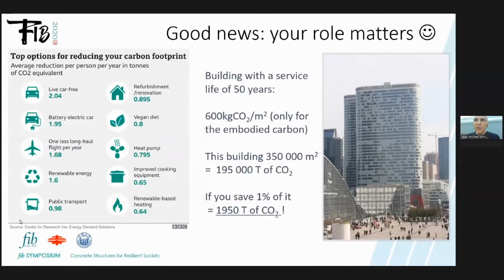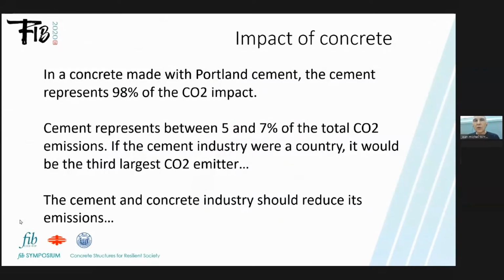If we look at concrete made with Portland cement, the cement represents 98% of the CO2 impact. It's the main part of the CO2 impact. That's why cement represents between 5 to 7%, depending on how you look at it, of the total CO2 emission. If the cement industry were a country, it would be the third largest CO2 emitter. Of course, it means that the cement and concrete industry should reduce its emissions.